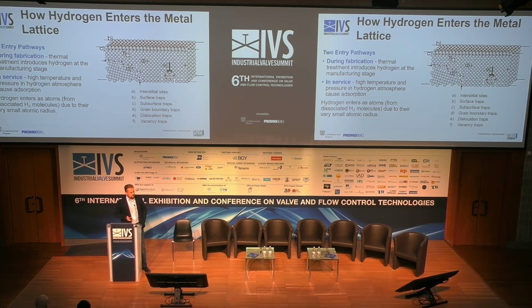But anyway, you can notice that hydrogen tends to concentrate in some small areas inside the metal, and it tends to create cavities. Those cavities are what makes metal brittle, let's say. It's not the best term to use right now, because what happens is that the metal loses part of its structure, and the more you go inside, the less metallic the structure actually becomes.